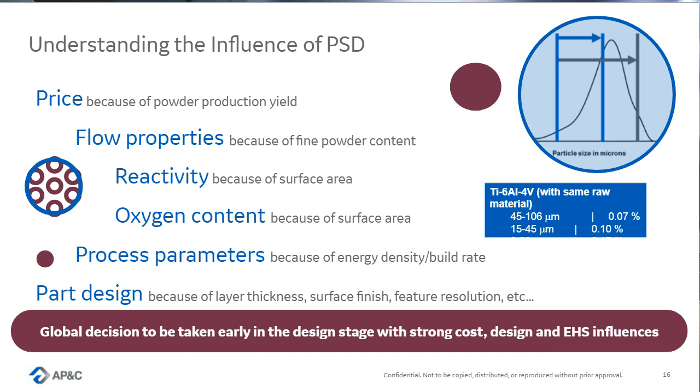How the powder will react is driven by the amount of surface available per mass. And as I show here on the left, with the same volume of particles, if you cut it into smaller pieces, you've got more surface, or more reactivity. We'll go into more detail about that in the next slide, so I won't talk too much here.